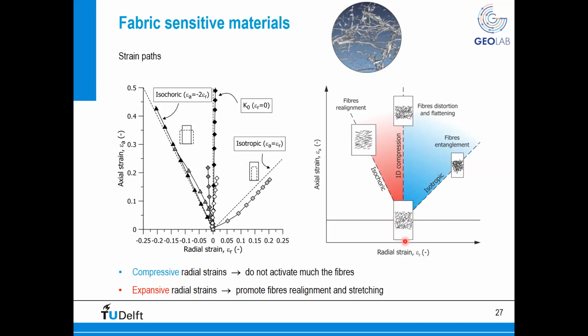So if you look here on the bottom right, you can imagine a sample of peat with randomly distributed fibers. And you can imagine that if you impose an isotropic compression test, you're basically squeezing the fibers from a lateral point of view, so the fibers are not activated much. But the other way around, if you impose an isochoric stress path, which means a triaxial undrained compression test, you are actually promoting lateral bulging and therefore stretching of the fibers. So that's why knowing the type of failure in the field is extremely important, because it will guide us on which type of laboratory test we want to place inside our test program.